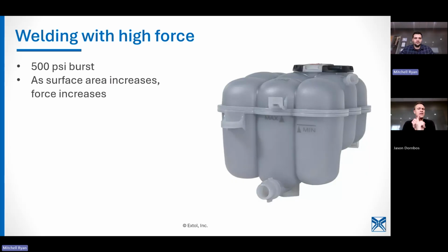That's why you need a lot of force when you're welding. Otherwise, it's going to take a really long time to get to your melt depth. You're pushing your part onto this hot tool, and without enough force, it's going to take a long time to get to the melt depth that you need. And then when you're trying to weld and seal them together, you need a lot of force into that weld geometry to get it to bond.